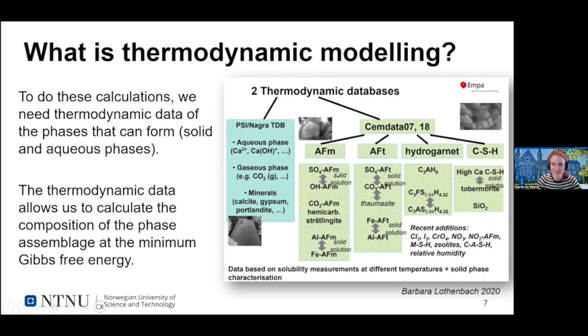This is a slide I borrowed from Barbara. And there you see that we use standard thermodynamic databases like the one from PSI for the aqueous phases, gaseous phases, and minerals. But then we also use a cement-specific database. And the most recent one is Cemdata18. And it gives us the thermodynamic data of your AFM phases, AFT, hydrogarnet, CSH. So the typical phases you would find in a hydrated cement.